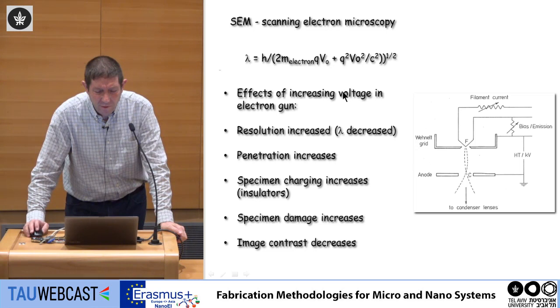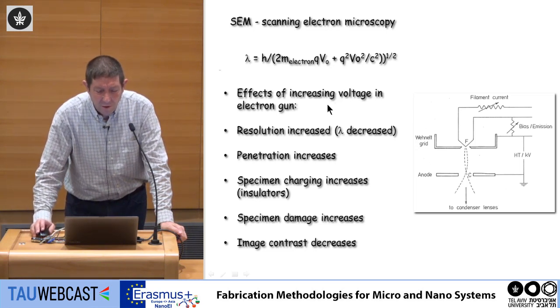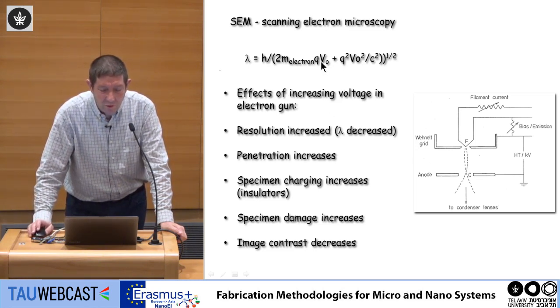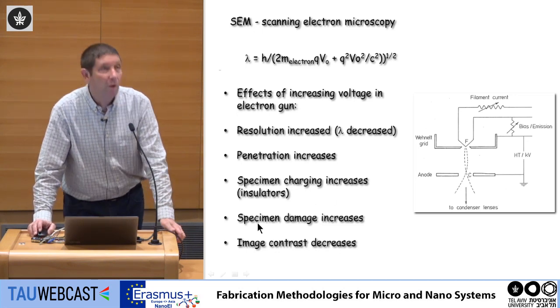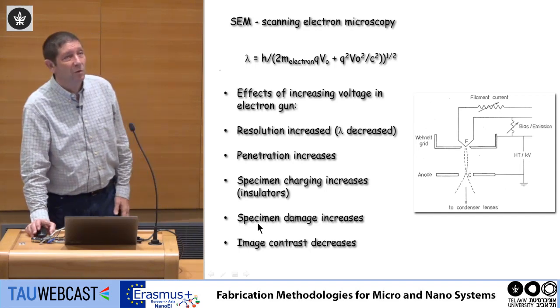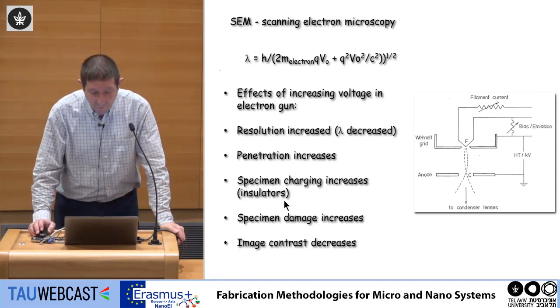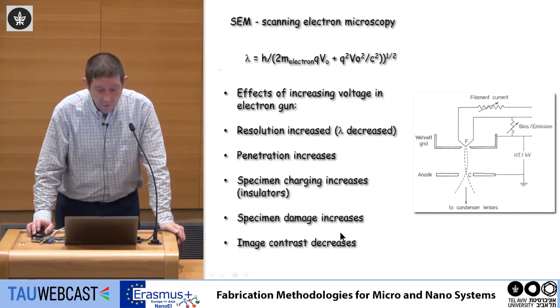So, the effect of increasing voltage in the electron gun. This is h divided by this number. If you increase the voltage, you reduce lambda, which means better resolution, and the penetration increases because you have more energy, but specimen charging increases in insulators. Also, because now you have electrons with high energy, you can introduce damage, and the image contrast may decrease.